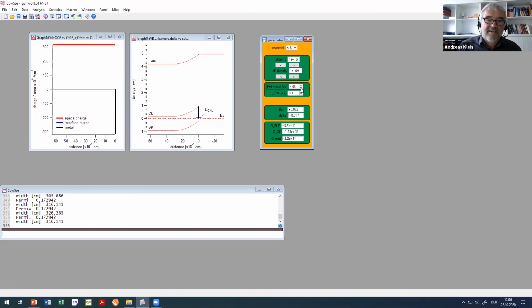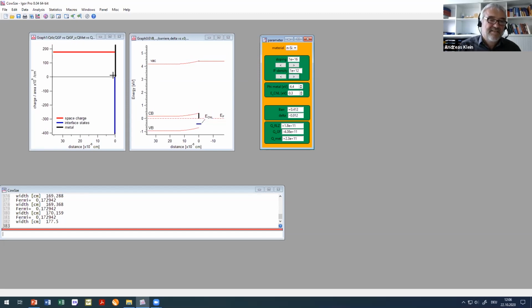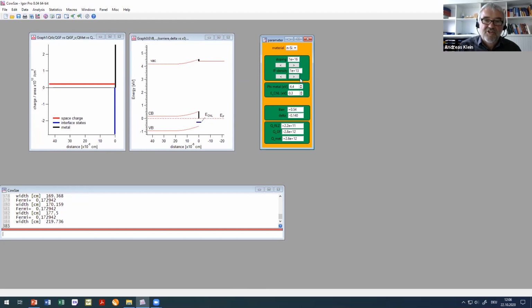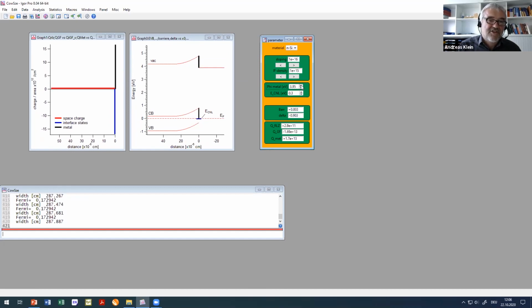Let's make it small, and now we increase the density of interface states, and you will finally notice that the interface states charge is increasing, and then eventually the Fermi level matches with the charge neutrality level at the interface. And now we have this dipole here, and if I change the work function of my metal now, the Fermi level at the interface doesn't change at all. It's only the work function of the metal which is changing, and the interface dipole which is really affected.